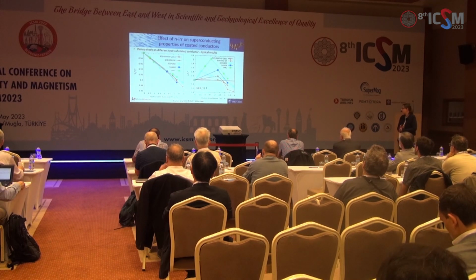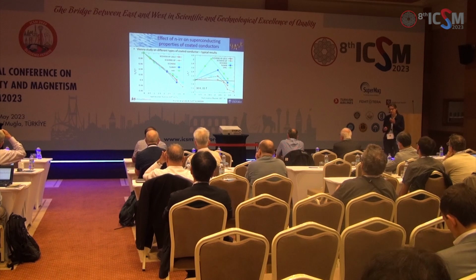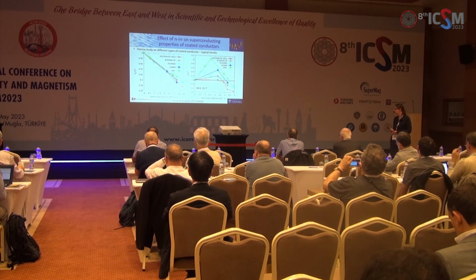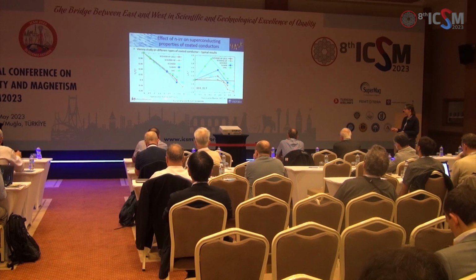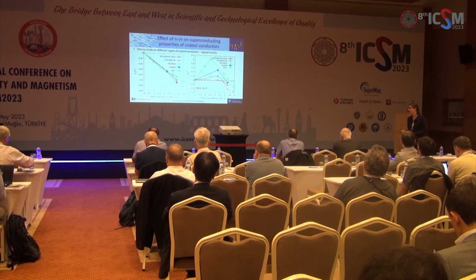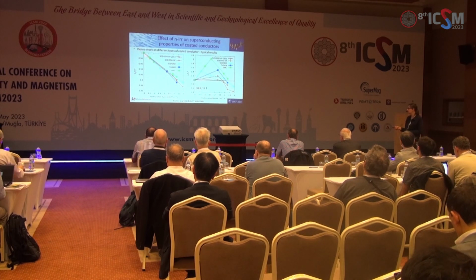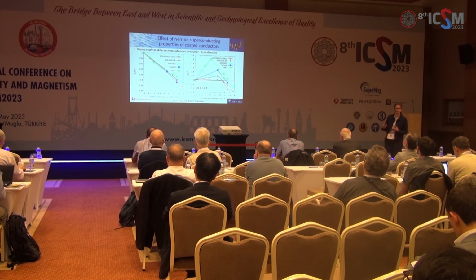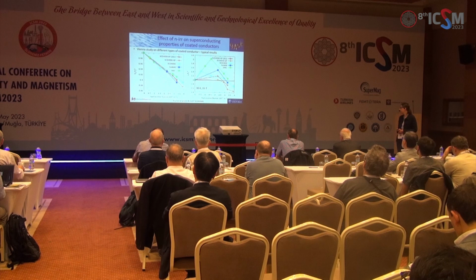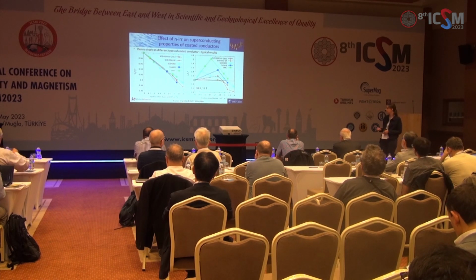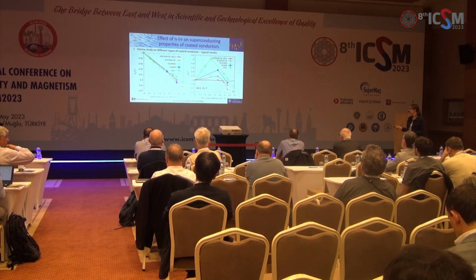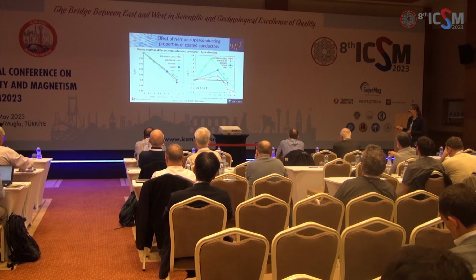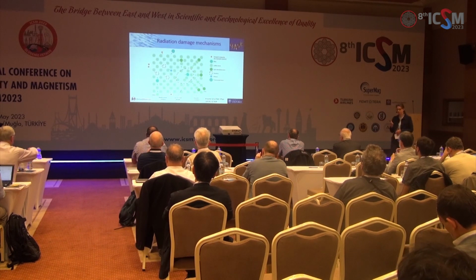So here's a graph from the Vienna group that shows how coated conductor properties change with fluence of neutrons. So this is how many neutrons have gone through the material, essentially, per unit area. So the transition temperature, this is normalized, decreases monotonically with the amount of neutron damage it's seen with the fluence. But the JC, or the IC of the material, does something a little bit more interesting. So this is in high fields at 15 Tesla. The critical current density goes up before it comes down again, which is quite interesting. But we'll have a look at why that might be the case.